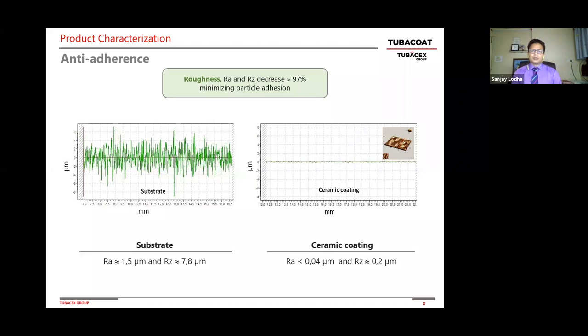Initially, we bring you the surface of the coated tube that's equivalent to a glass finish, a mirror finish, very smooth. And we know the smoother the surface, there is less resistance to the flow, there is less resistance for the particulates and metal compounds to deposit on the surface and begin the fouling process. So by having this smooth surface, we're minimizing any tendency for the particulates or any other matter to deposit and begin the fouling and the corrosion process.